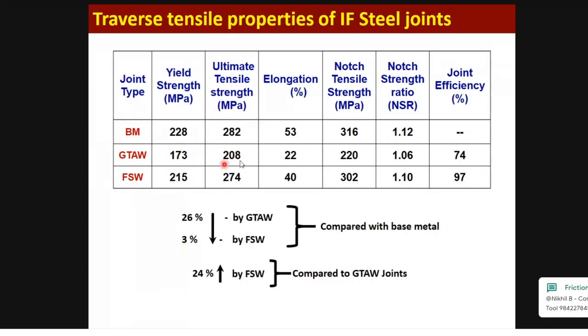So because of this microstructural difference, changes in the fine formation, you see that this base metal is 282 megapascal, and when you do the TIG welded joints it gave 208 megapascal, and the FSW it is 274, very close to matching with the base metal tensile strength. But in the TIG welding, it is 26% lower, but here it is only just 3% lower when compared to the base metal strength.